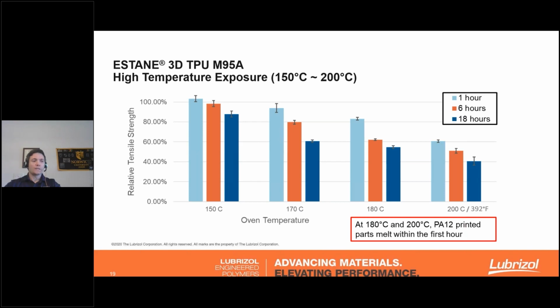Something that I consider to be even more impressive than the slightly increased temperature performance for a very long period of time was the ability of our material to withstand significantly increased temperatures for shorter periods of time. So on the screen is illustrated what happens when the material is brought up to 200 degrees Celsius, or just under 400 degrees Fahrenheit, for up to 18 hours. And again, while you see a decline in material properties, specifically tensile strength, the material itself does survive and it remains structurally intact, which is really impressive for a TPU.